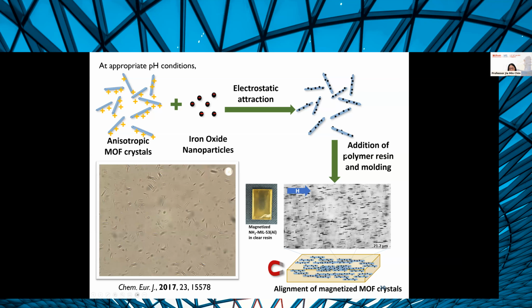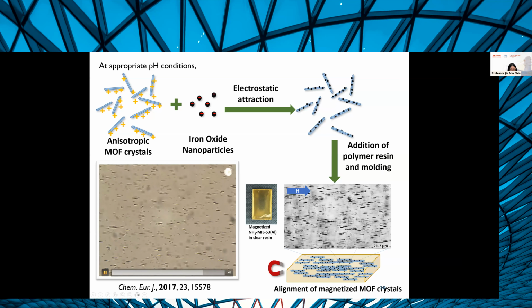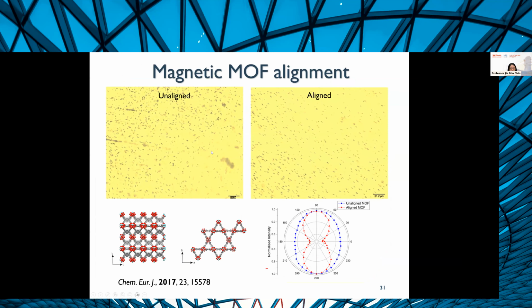We then dispersed this in different types of polymer resins, and then we molded them in the presence of a magnetic field. And you can see here a little video of how rapidly they can align. Of course, how rapidly they align depends on the viscosity of the liquid, but we were still able to very easily cause this orientation even in really viscous resins and photopolymers. So, sorry. We found that we could orient these MOFs inside a resin. In this case we used NH2-MIL-53(Al), so you see that here they're aligned in the diagonal direction and here they're all randomly oriented.